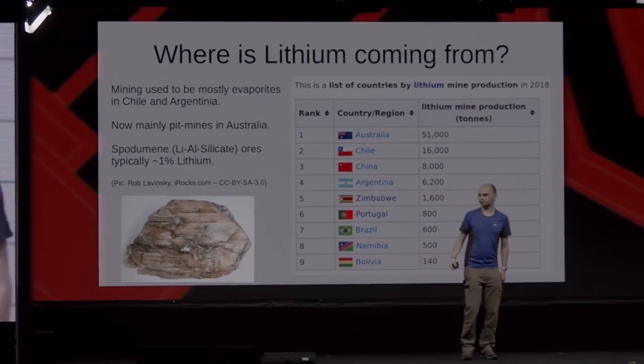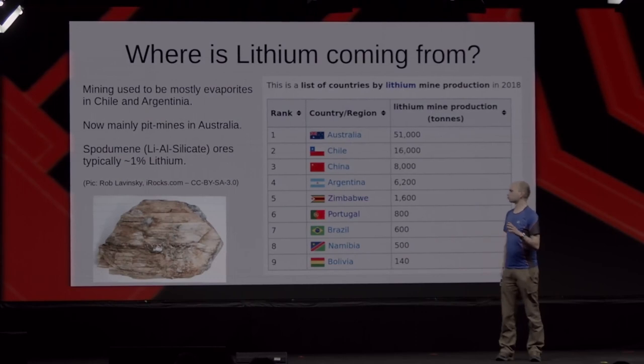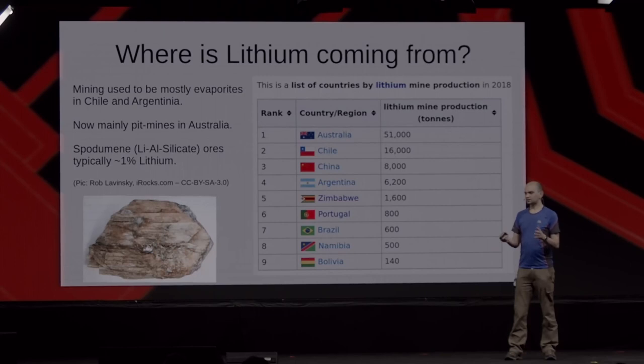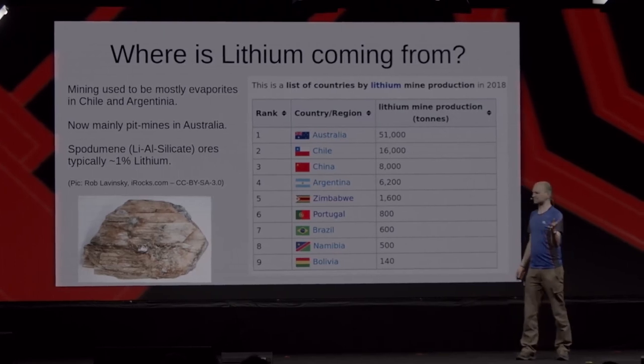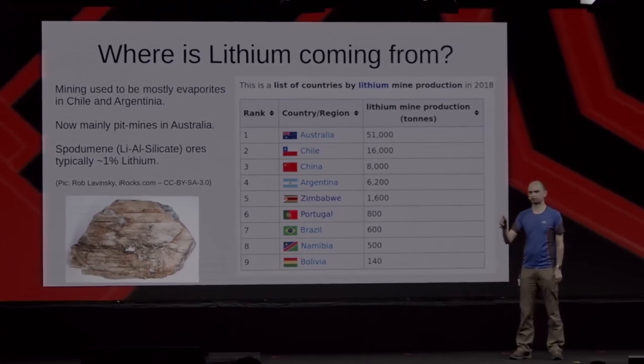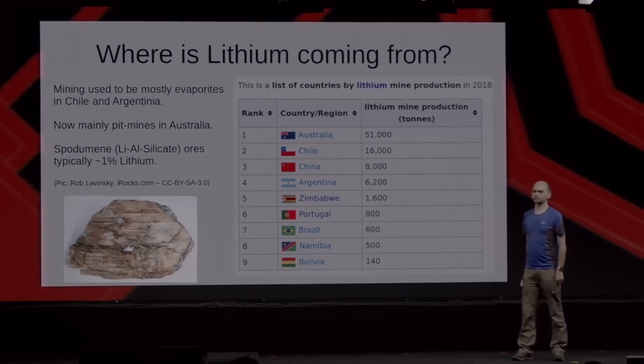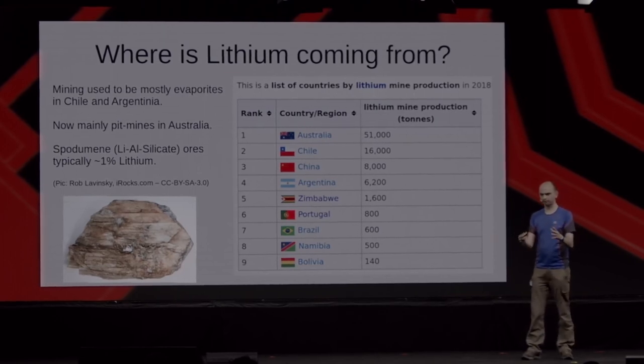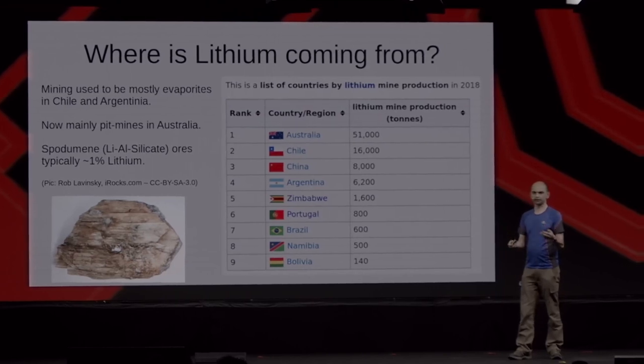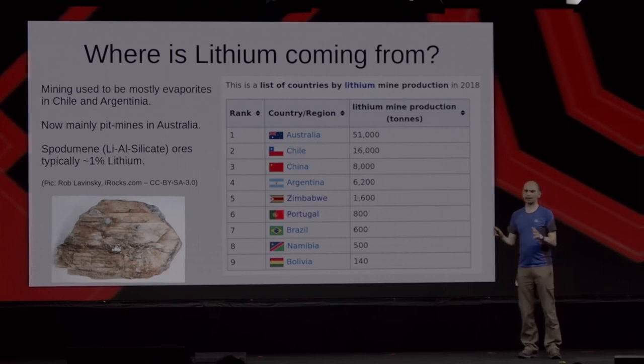In Australia, what they're doing is mining ores. Ores like this one here. Spodumene, this is a lithium aluminium silicate. And in theory, the ores themselves could contain about 6.8% of lithium by weight. I know that's lithium oxide, so it's about half that, so about 3 to 4% of lithium. But typically, you will get maybe 1% of lithium by weight. And that's just for the ore. You have to get to the ore itself. And when you mine something, you not only get the ore itself, but also other stuff. So actually, you need to mine maybe about 1,000 tons of stuff in order to get 1 ton of lithium. And that sort of thing is done on a large scale in Australia. And that's where, as you can see, it's coming from. And most of that is, by the way, from Chinese firms, because most of the batteries are made in China.